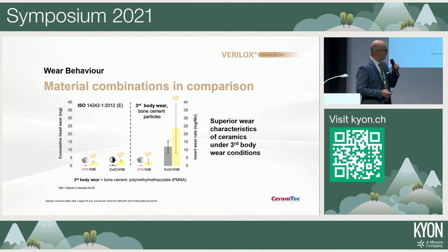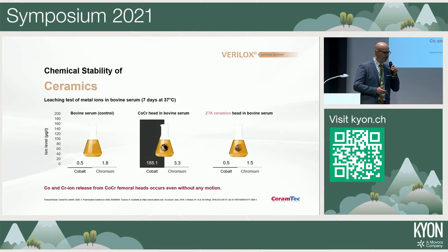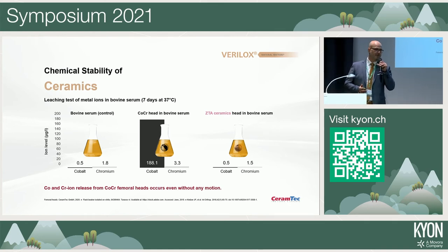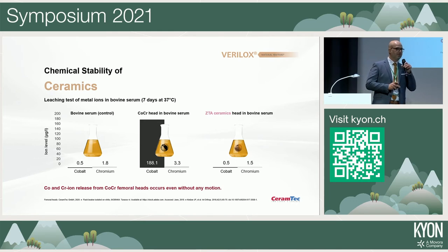But let's go away from the mechanical testing to the chemical and biological testing. Another advantage of ceramic is the low release or nearly no release of metal ions. And this was a test where we tried to do leaching of the components. We used two groups, with the testing components, metal heads, ceramic heads, which were put into bovine serum, and the reference group, the control group, was the bovine serum itself. And what you see there is, in ceramics, you get the same results, no significant difference with the pure solution, so you don't get any measurable ion release, while if you take the metal components, you can see a significant increase of cobalt ions in the bovine serum, and also for chromium, you see an increase.